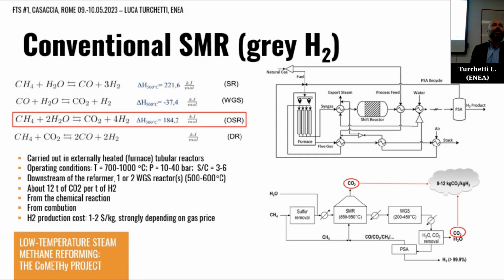And the color gray lets us understand, which is not very good for the environment, actually, because basically the steam reforming is also a complex set of different reactions. I would say the most important one is the one you see here. You combine methane with steam and high temperature over a catalyst, and you get carbon dioxide and hydrogen. This process is strongly endothermic, which means that it requires a lot of heat to be carried out.